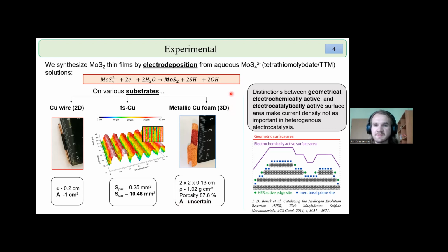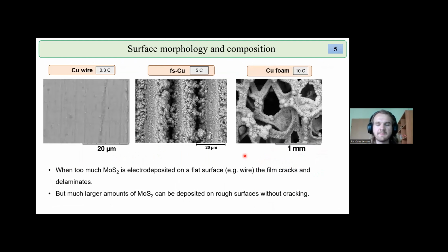And the reason I'm talking about surface area is because in heterogeneous electrocatalysis, it is very important to distinguish between the geometrical, the electrochemically active, and even the electrocatalytically active surface area. As shown in this graph, which is a citation from a paper, the geometric surface area can simply be thought of as the surface of the material. The electrochemically active surface area is the area on which charge can accumulate, and the electrocatalytically active surface area in this graph is represented by active sites. In heterogeneous catalysis, the process does occur on active sites typically, so the electrocatalytically active surface area can be very different from the geometrical surface area and even the electrochemically active surface area.